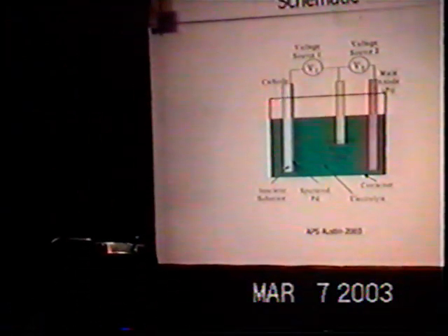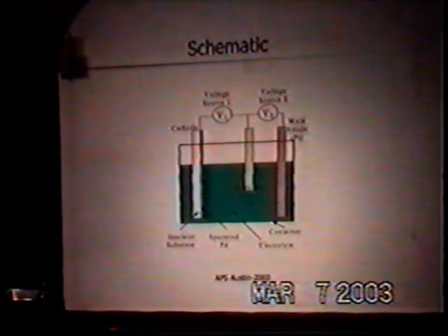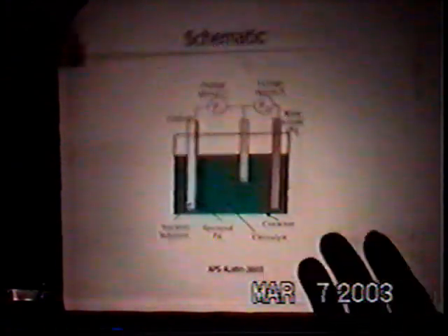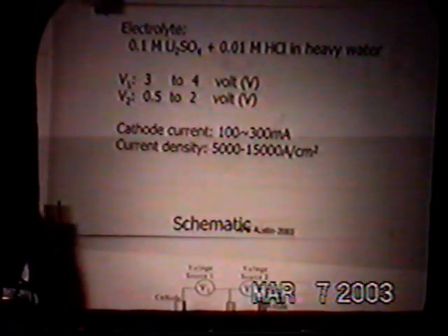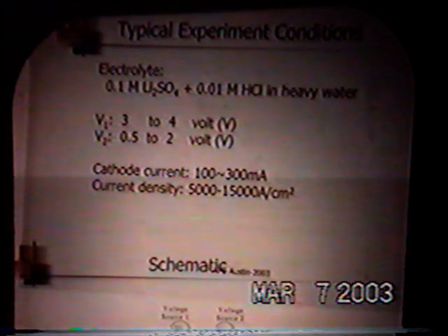The main anode is here, the cathode is a thin film, sputtered on to start with, but now there's an associated palladium anode. Since it has separate power supplies, you can control the relative voltage across, and it builds up the palladium by plating out onto the surface of the thin film. The typical conditions are V1, between the auxiliary anode and the cathode, 3 to 4 volts, somewhat lower from the main anode to the auxiliary. We're using lithium sulfate with added HCl for the transporter.